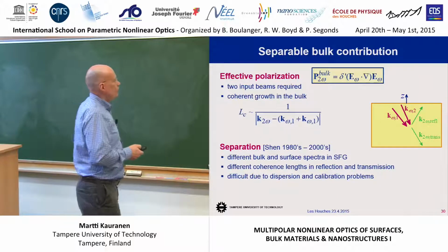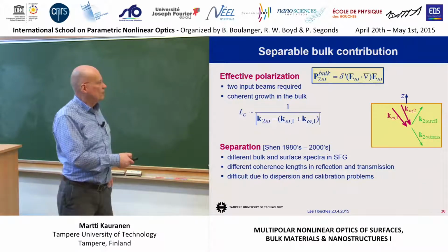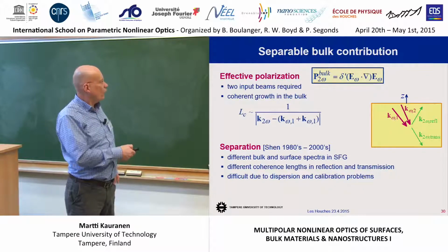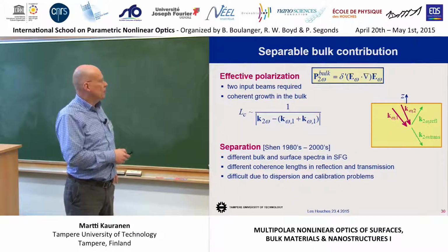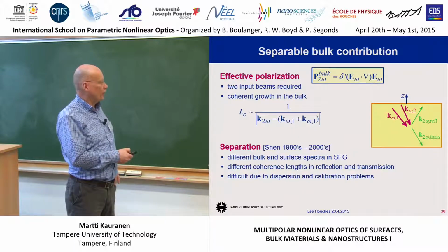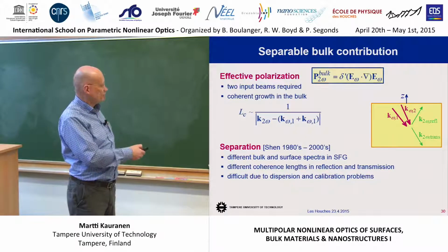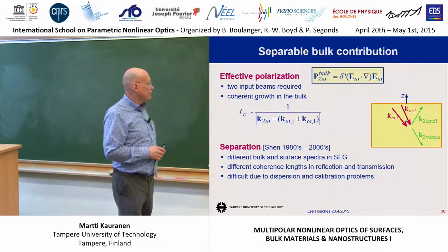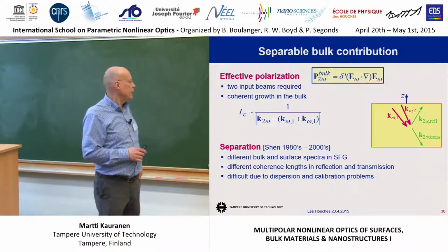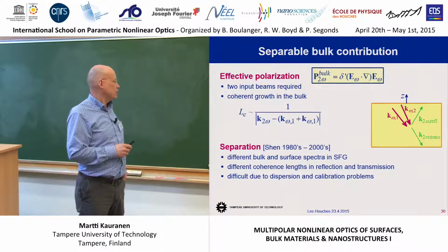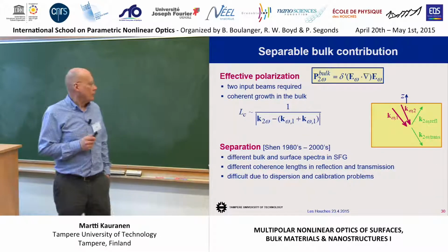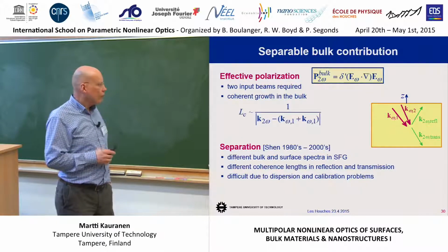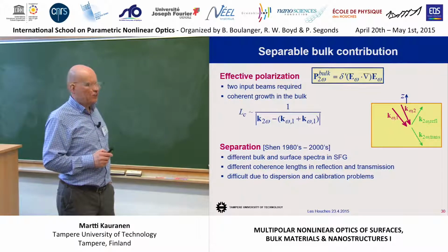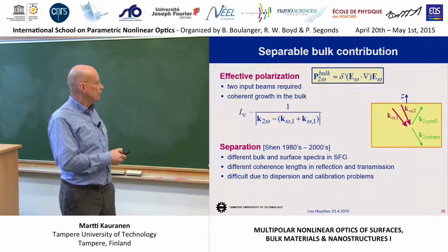And then the growth of this signal depends somehow on the coherence length of the interaction within the bulk. So it depends on the difference between the k vectors at the second harmonic frequency, and then the sum of the fundamental ones; this should be 2 here, but this is the phase mismatch. And the person who worked on this a lot, from the 1980s until the early 2000s, was again Ron Shen, who is really the pioneer of surface nonlinear optics. And he did a lot of different experiments trying to somehow access this contribution.